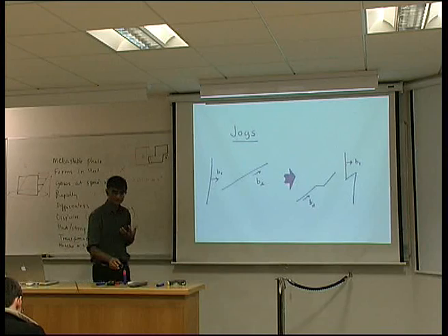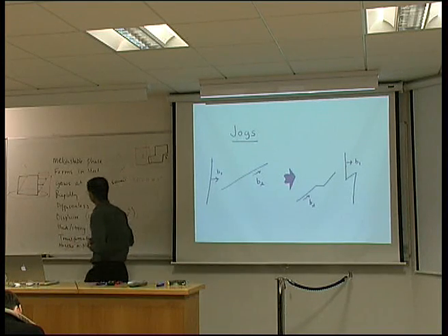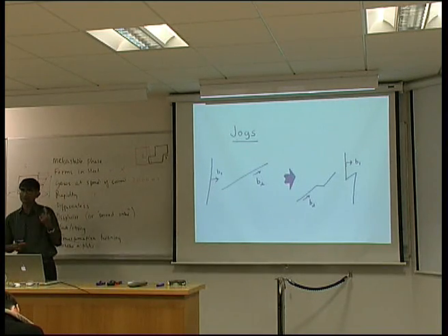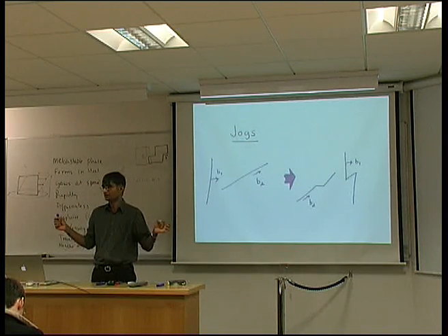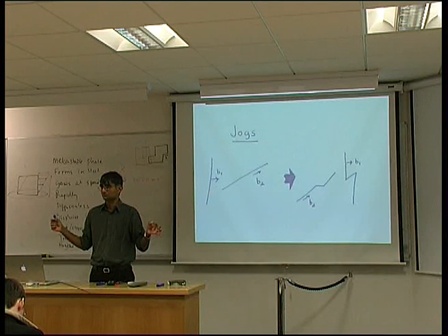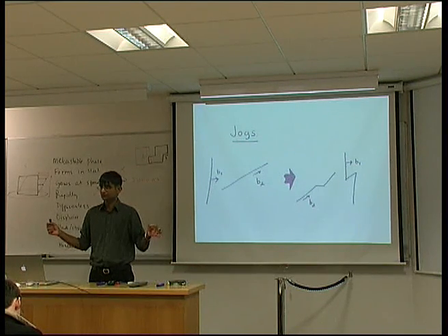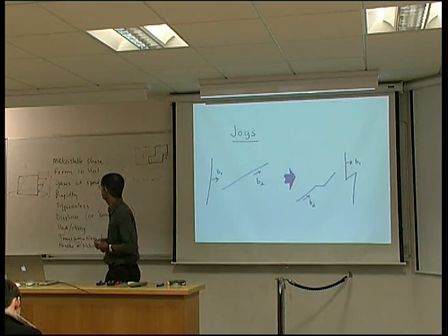So, this is something that is incredibly important: in order to get martensitic transformations, we must be able to find one line in the interface which is perfectly coherent. That means it is undistorted and unrotated, an invariant line.